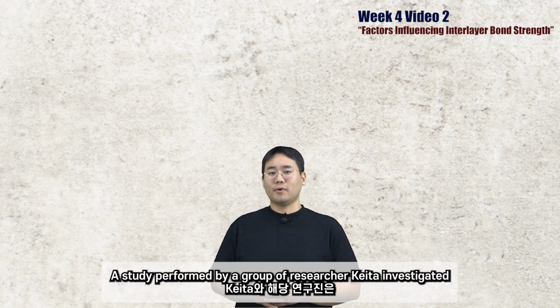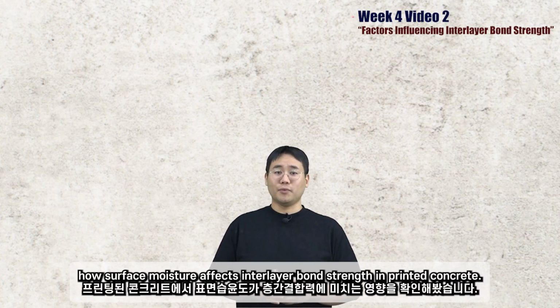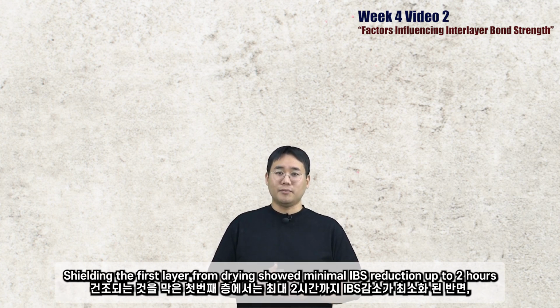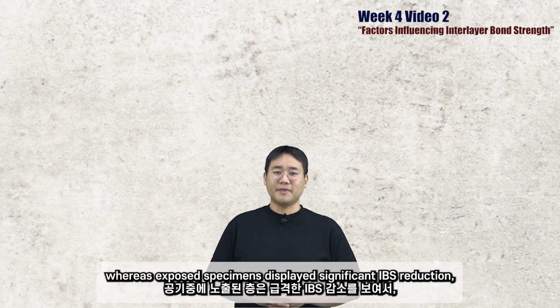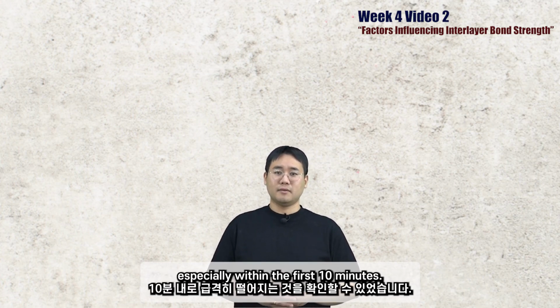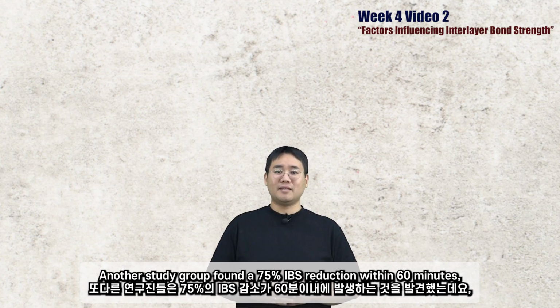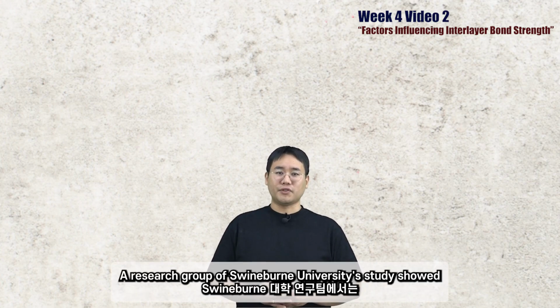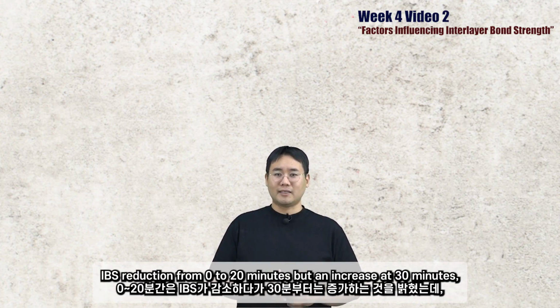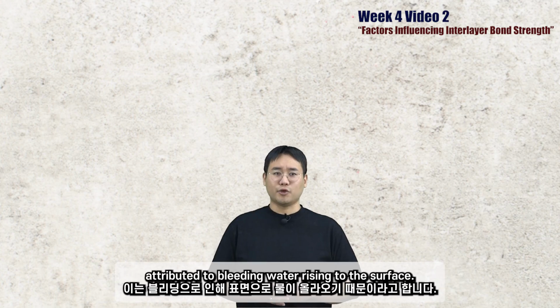A study performed by a group of researchers investigated how surface moisture affects interlayer bond strength in printed concrete. Shielding the first layer from drying showed minimal interlayer bonding strength reduction up to 2 hours, whereas exposed specimens displayed significant interlayer bonding strength reduction, especially within the first 10 minutes. Another study group found a 75% interlayer bonding strength reduction within 60 minutes, mainly due to the surface moisture loss. A research group at Swinburne University showed interlayer bonding strength reduction from 0 to 20 minutes, but an increase at 30 minutes, attributed to bleeding water rising to the surface.